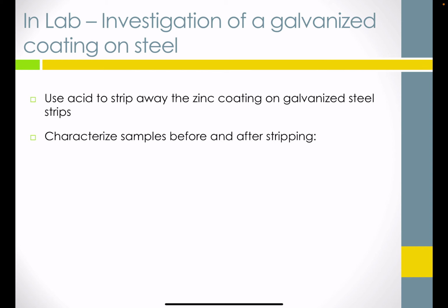Okay, so in lab you can see here that we're going to investigate galvanized steel coating on steel. We're going to use an acid strip to digest away the zinc coating. We've justified the electrochemical steps there a moment ago. This will lead to a weight change and certainly transform the optical microscopy result of the zinc. So we'll lose that leafy granular structure that we saw in the diagram a moment ago, and we'll expose bare steel in doing so. So we'll end up doing characterization before and after this stripping process.